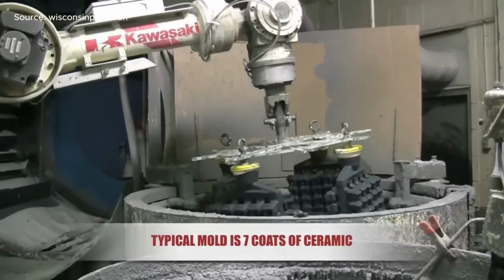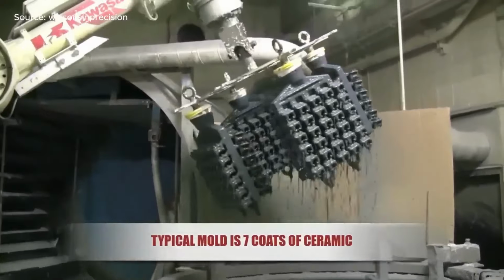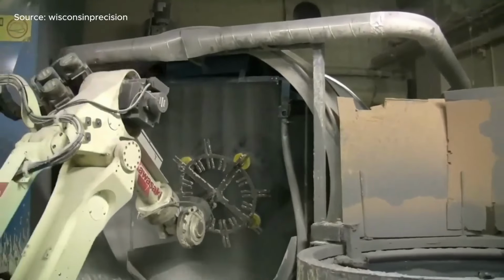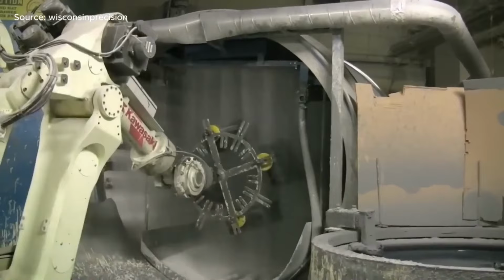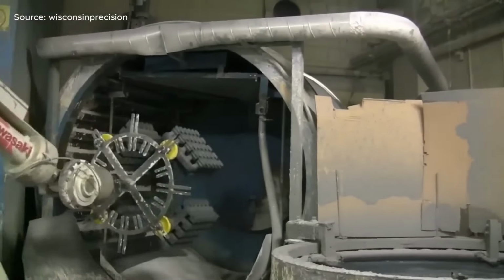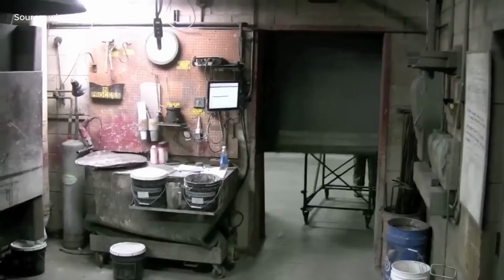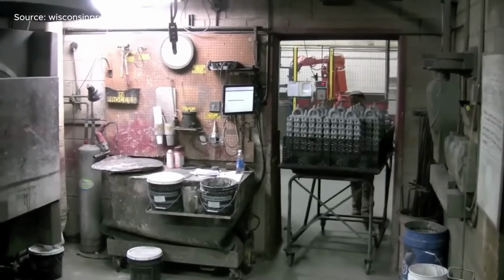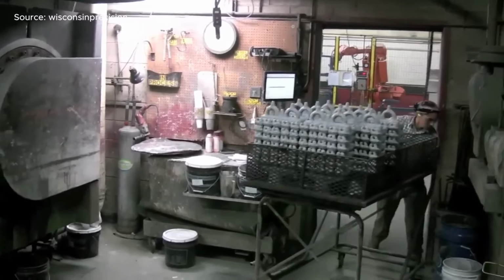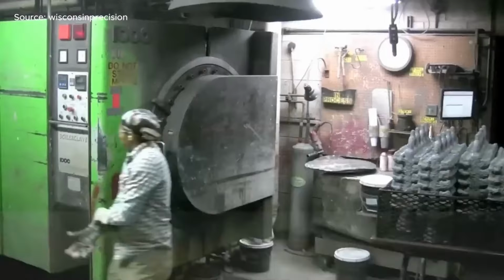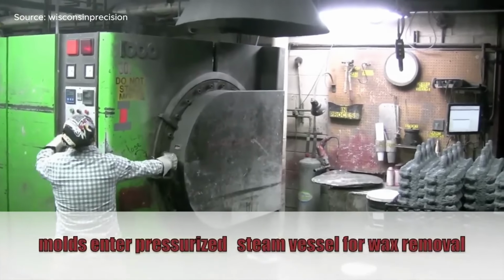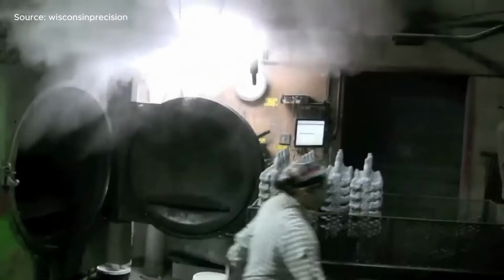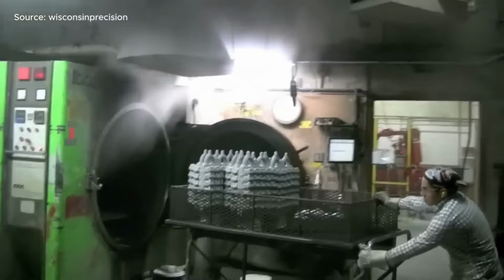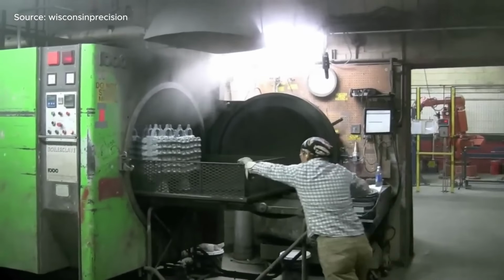Ceramic mold formation. The assembled wax patterns are dipped into a fused silica slurry to create the initial ceramic coating. This coating captures fine surface details. After dipping, stuccoing is applied using fused silica particles to build additional layers of ceramic. Mold strengthening. The mold is built up through repeated cycles of dipping and stuccoing, typically forming 7 layers of ceramic. Once fully coated, the molds are left to dry and harden.